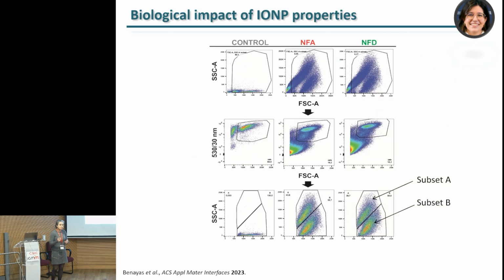We also evaluated the process of internalization by using flow cytometry. It's a very useful and potent technique used in biology and biochemistry. What we found here, as you can see, basically the SSC is the side scatter that is telling us how complex is the particle that we are evaluating. So when the cell gets more complex, it gives you a higher value of the side scatter, and that's what we got. For those cells, you can see here, NFA and NFD treated cells, we could segregate the original population into two subpopulations.